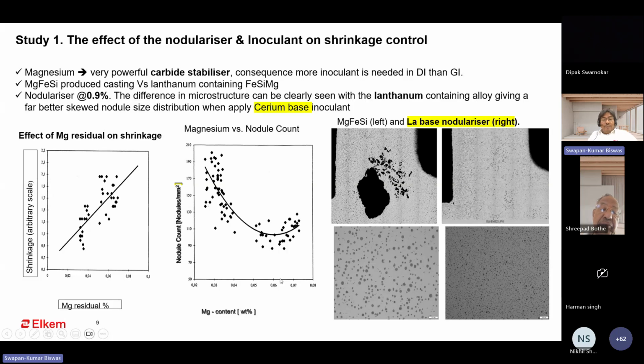And the other is magnesium content with nodule count. You have seen that lower residual magnesium always gives a high nodule count. That means a high nodule count helps to control your metallurgical shrinkage. On the right side, there are two pictures, with two different packages used. One is the left side graphite structure.